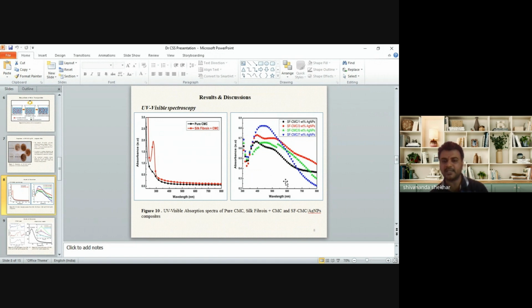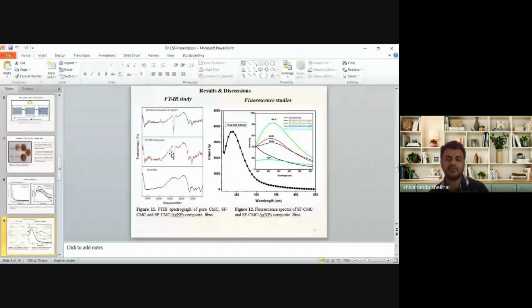So we have obtained an absorption band around the 400 to 450 or 470 range. This is due to the formation of AgNPs present in the silk fibroin solution. So these are the SPR band, surface plasmon resonance band, which reveals the formation of AgNPs in the matrix. Then we have done FTIR studies and fluorescence studies also.